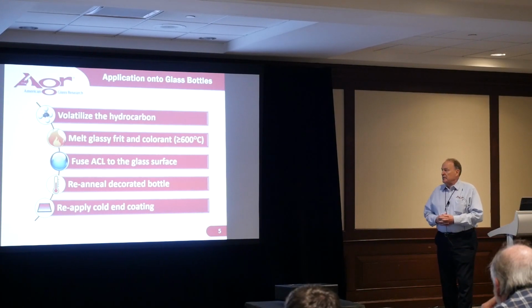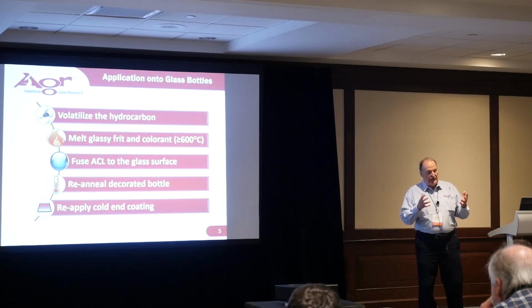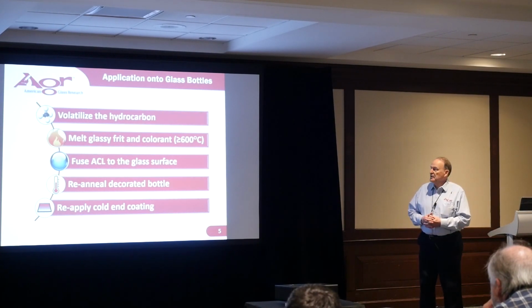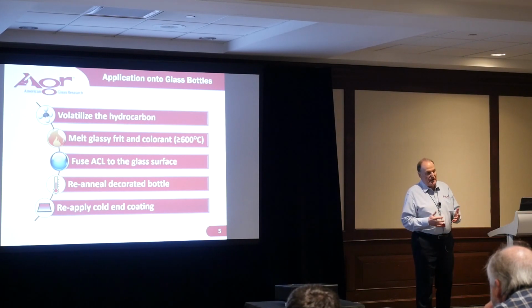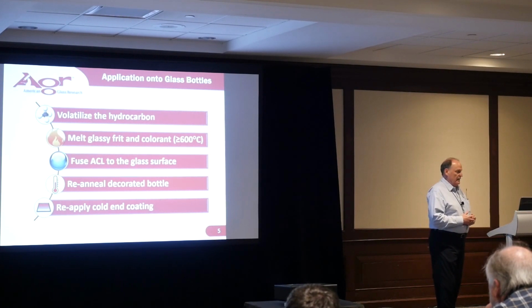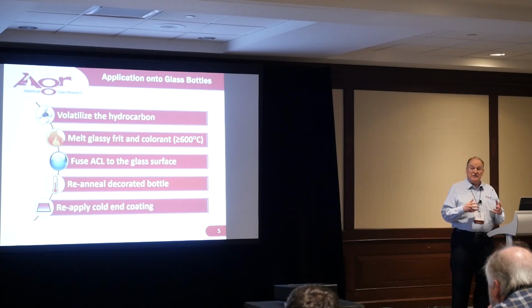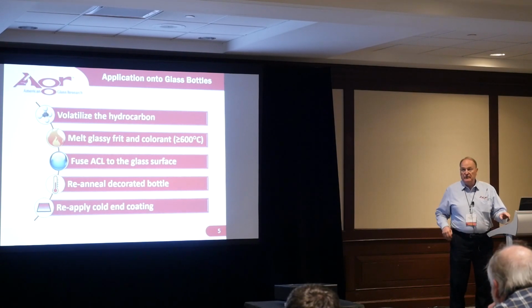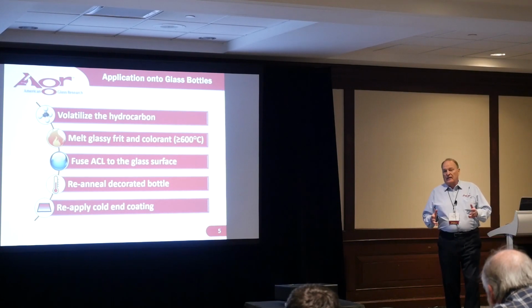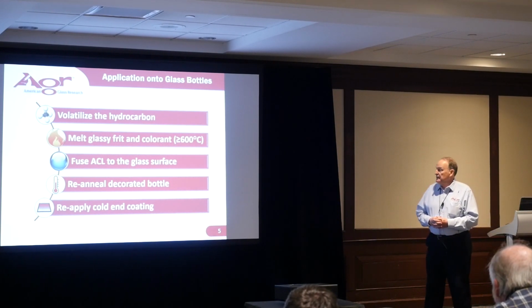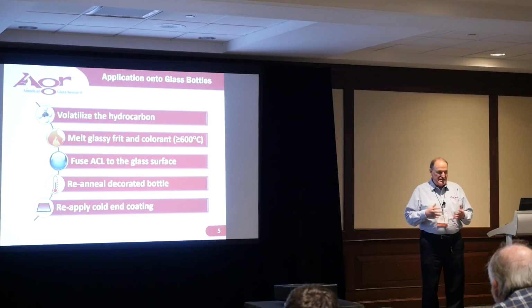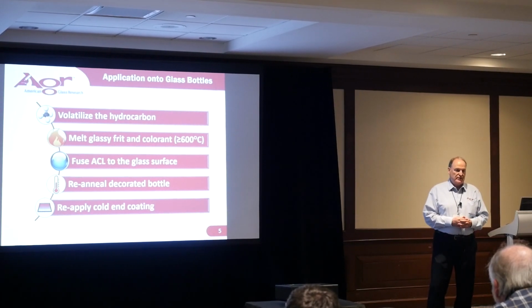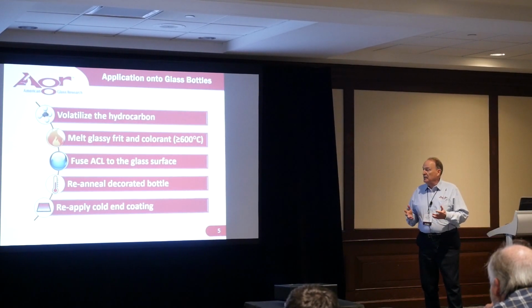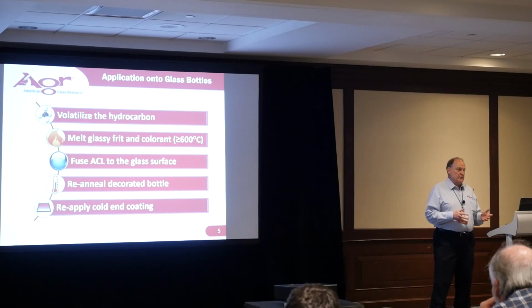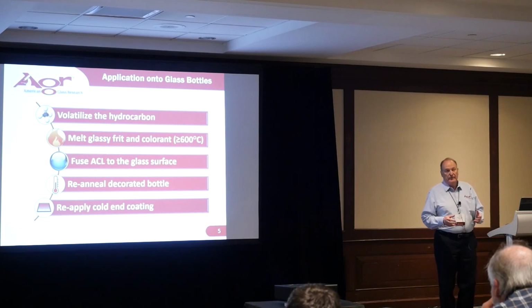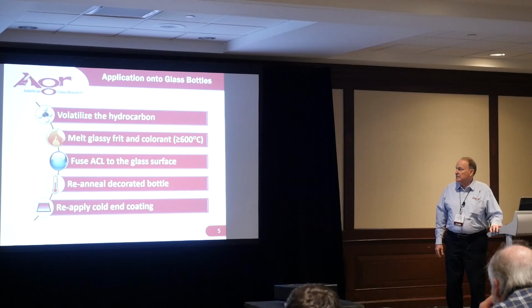These decorated room temperature bottles are then slowly heated up to some elevated temperature. During the initial stages of the heat, the hydrocarbon carrier or this dispersing agent would be volatilized. The glass bottle is then continued to be heated up to a temperature somewhat in excess of 600 degrees centigrade, at which time that low melt temperature frit and colorant are now molten, fused to the glass surface.